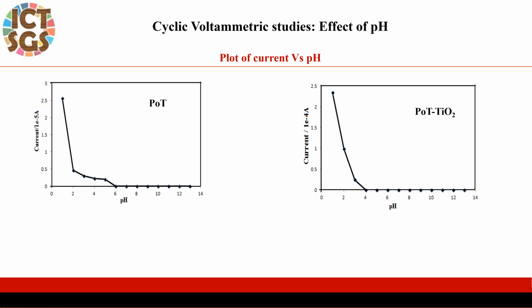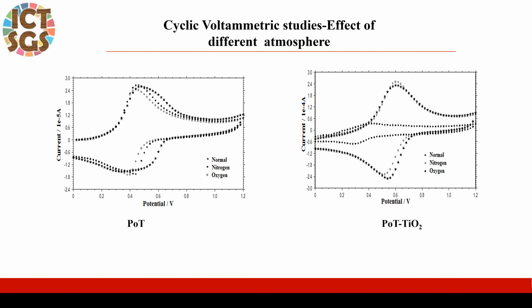The effect of pH on the voltammetric response was studied over the pH range 1 to 13. The optimum pH for good sensitivity appeared to be pH 1 for both PoT and PoT titania nanocomposites. The effect of different atmospheres, that is oxygen and nitrogen atmosphere, was studied. This study suggests that the PoT modified GCE slightly enhances the electrocatalytic activity in the nitrogen and oxygen saturated buffer.